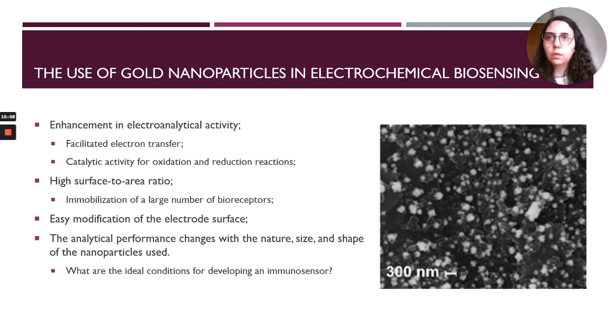Usually these particles promote an enhancement in electroanalytical activity. They facilitate electron transfer, and they provide catalytic activity for the oxidation and reduction of many different species. Also, we have a very high surface to area ratio, which allows us to increase the number of bioreceptors we can immobilize in the electrode, and allows easy modification of the electrode surface using thiol groups, for example. And the analytical performance can be tuned depending on the nanoparticle nature, size, shape. So in this work, we have decided to study different conditions from a protocol for electrodepositing gold nanoparticles on an electrode surface and its influence on the development of an immunosensor.